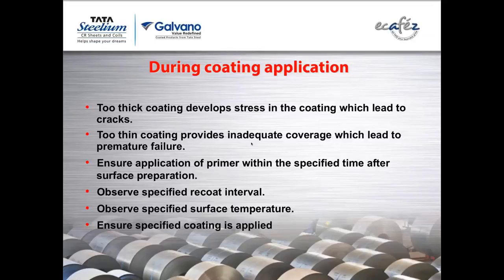intercoat adhesion. So naturally you might have seen some problems, or there was one photograph also earlier if you remember, that the primer coat is intact and top coat is coming like a peel of banana. This is a clear-cut indication of they have not observed the recoat intervals. So that is very important. In some case of primers, you will find the recoat interval other side open. So even if you do it after a week or 1 month, there is no issue. But this you need to read it on the technical data sheet, discuss with your coating supplier, and then you will not have any problems.